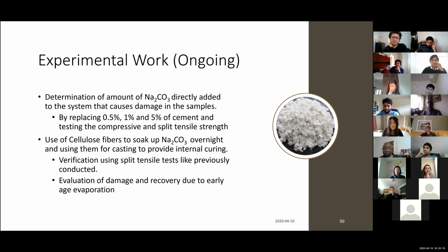So if hopefully it works, in the long term we might end up losing the cellulose fiber itself. The only hope I'm having is that we have one particular type of cellulose fiber that will not have this degradation problem. Namely, that's the PBF. So worst case scenario, if degradation is an issue, we can fall back on the PBF because of the refining, the lumen has been removed. So it doesn't have that problem compared to the regular microcellulose fiber. But at this point, it's still all conjecture because we are not sure if the amount of cellulose fiber we are using can actually bring enough of the sodium carbonate.